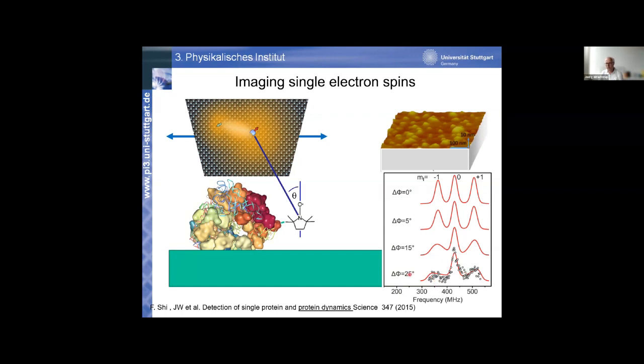And this red curve tells you that over the course of the experiment, which takes roughly a minute or so to measure each of these points, this angle theta was actually changing on average by 25 degrees. This change of the angle theta mostly comes from the flexibility of the subpart of the protein this electron spin is fastened to.